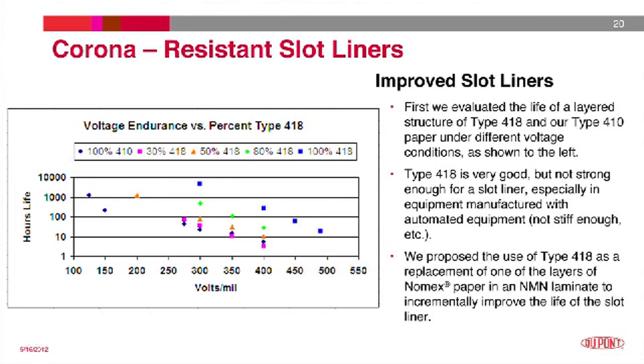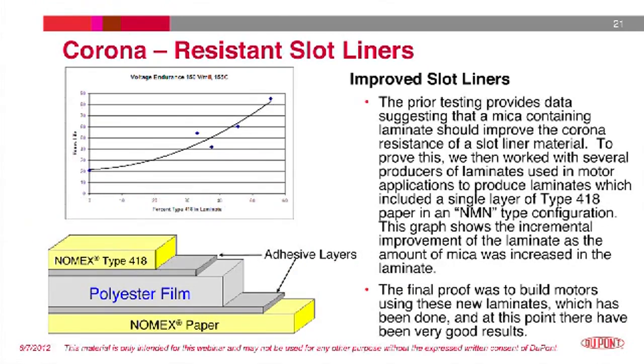Type 418 has very good voltage endurance, however, it is weak mechanically. So, to help provide an optimized solution, we proposed an NMN laminate where one of the two layers of Nomex paper would be replaced by Type 418 to incrementally improve the corona resistance of the slot liner to help improve the life of the motor. This testing proved that by substituting portions of the laminate with Type 418 papers, we could improve the life of the laminate versus that of typical NMN laminates.